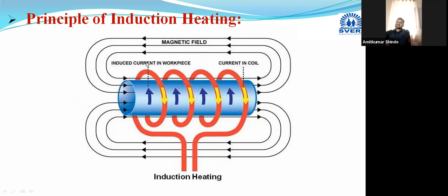Due to this magnetic field, what will happen? Eddy currents will start flowing through this component. Due to skin effect, eddy currents flow through this component, and layer by layer heating will occur. This is the skin effect.